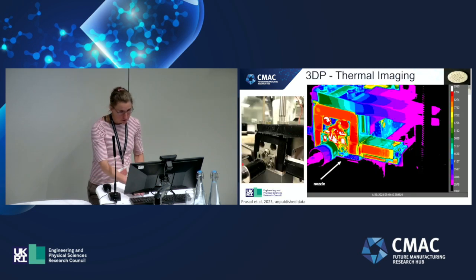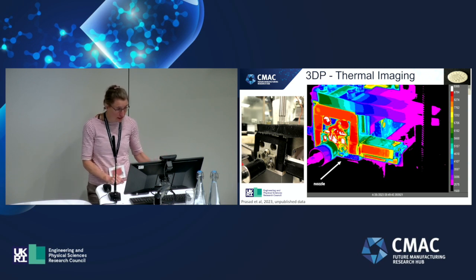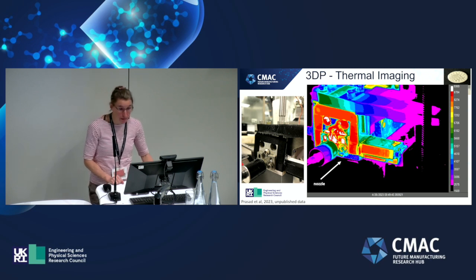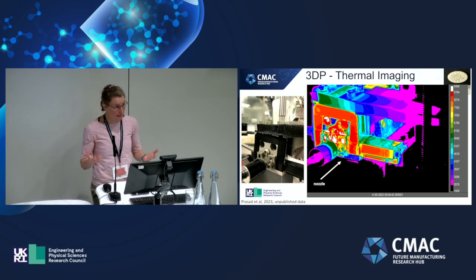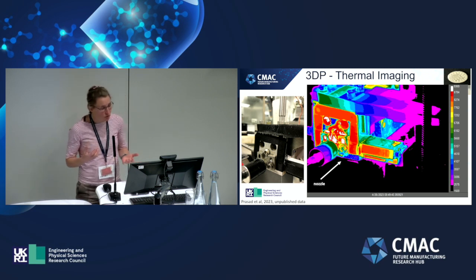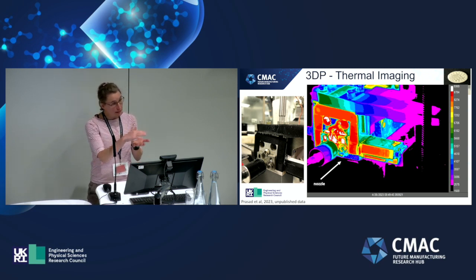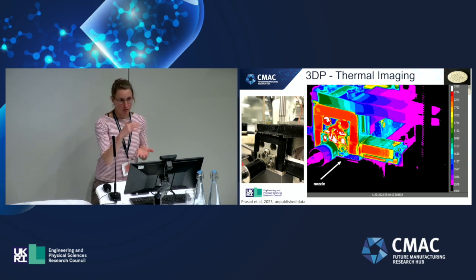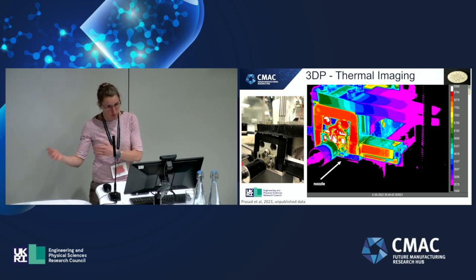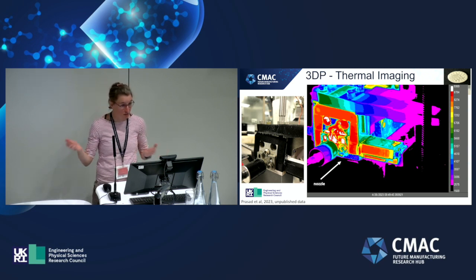So temperature is obviously one of the key process parameters in the 3D printing space. We've looked at thermal imaging of these 3D printing processes. So I've already mentioned that the stickiness is related to temperature, and also that the stickiness is important for the success of the 3D printing as such. But it's also important when you think about the layer-to-layer adhesion of a tablet that you're printing. So if you can design your process so that you're getting either very good adhesion or not so good adhesion, this can affect the disintegration of your tablet, and therefore you could control your product performance in that way.